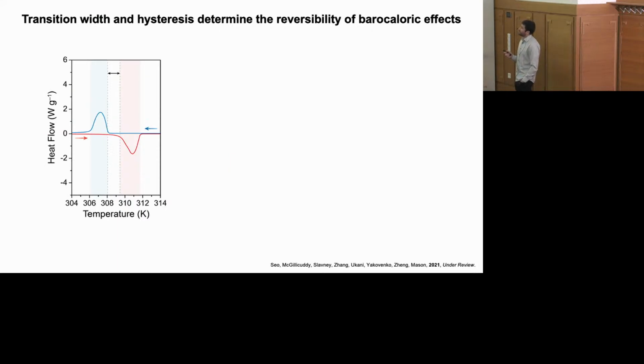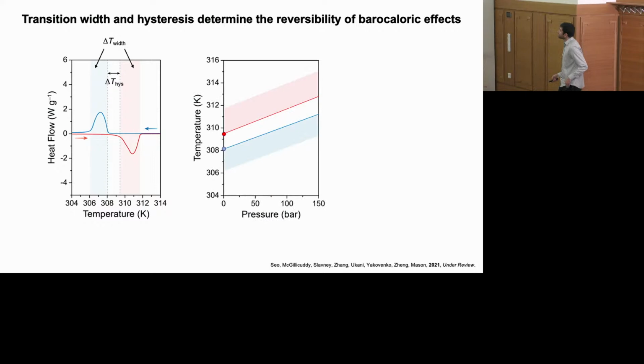And so in evaluating the properties of these materials, there's 2 features of these DSC curves that are really important. One is the width of these transition peaks, and the other, as I mentioned, is the hysteresis associated with these transitions. And so one thing my lab has spent a fair bit of time on is trying to understand what are the specific factors that contribute both to hysteresis and transition width? What is actually intrinsic to the composition of a particular material, and what is extrinsic? Meaning, what depends on how you pack your sample together, particle size, degree of thermal contact in the experiment, and other factors like that.